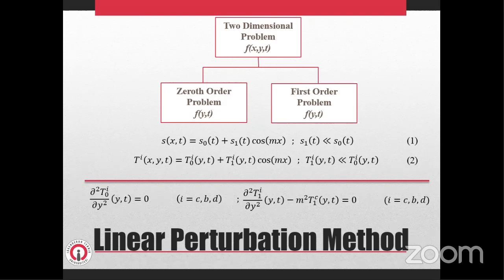Experimental observations indicate that development of the solidification front exhibits sinusoidal-like perturbations. It is anticipated that this non-uniform shell growth could be a response to a pre-existing non-uniformity in the heat flux drawn from the mold surface. Subscripts 0 and 1 define the x-independent zeroth order process and first order process. Since the perturbation is sufficiently small compared with the unperturbed process, the other field quantities such as temperature fields and solidification front are defined in the form of expansions in equation 1 and equation 2.